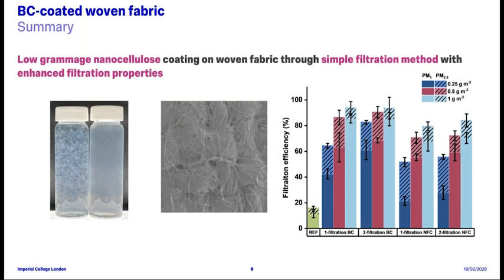So by far, we have proved that a robust and low grammage bacterial cellulose coating can be vacuum filtered onto a woven fabric to enhance its filtration properties without compromising the moisture permeance across the protective garments. And if you have noticed, we have been only using water as the filtering medium all this time, as this is an easy and obvious choice given the hydrophilic nature of nanocellulose attributed by the hydrogen bonding between water and the exposed hydroxyl groups. However, we are also aware that the current bacterial cellulose coating layer is not perfect.